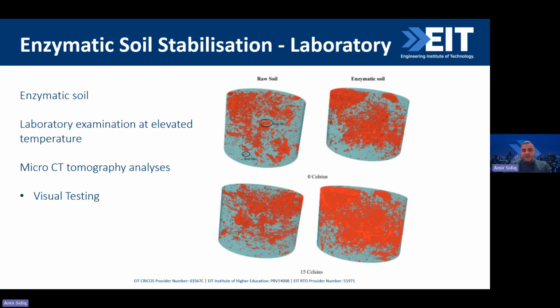So by using the micro CT, the very first thing I tried was to get the sample, separate the void and the solid, and then combine these two together to develop a 3D section. Here we can see the red spots are the void, and the light green ones are the solid. This is for the raw soil, and this is for the enzymatic. And then you have the different temperatures from 0 to 60 degrees at 15 Celsius intervals.